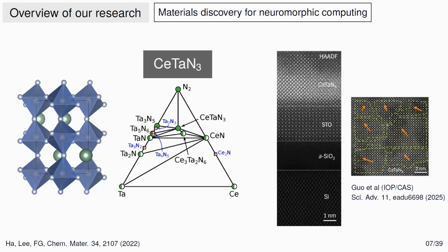And the interesting thing on nitrides is that the perovskite has a structure which is a formula unit ABX3. So when you have nitrogen, which is 3-, the N3 brings us to 9-. So the A and B sites should be adding up to +9, okay? So that means that the two cations are extremely oxidized, and that's very difficult to achieve. So we did some thermodynamic studies with basically DFT calculations, and we predicted that this object should exist, should be stable, and should be a ferroelectric semiconductor.